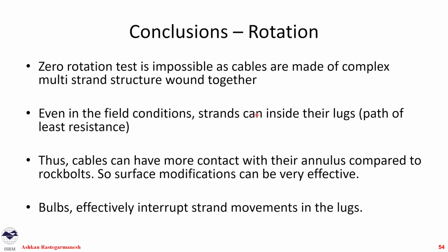But we can actually learn from the observations that because cables are in contact with their grout lugs or resin lugs for longer, we can use something like surface indentations to use these connections. Remember, rock bolts, because they have those fixed ridges on them, when you pull them out, they scrape the whole grout annulus or resin and they damage everything. So you basically don't get that much resistance. But for cable, even after 100 millimeter of test, as we saw during my presentation, you have basically most of your lugs in place. And especially towards the entry point, they are undamaged. So that means that the cable was traveling more or less inside its own section, compared to, again, rock bolt, which basically scrapes everything off.